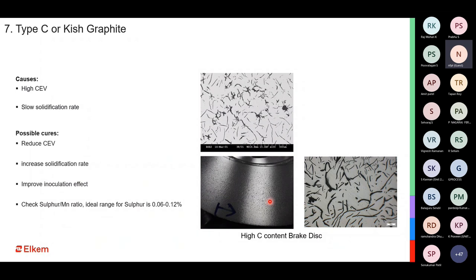When you machine a casting which has type C, you can see this type of pit marks, which are basically graphite getting pulled out because of their concentration in a few locations. How do you resolve it? Of course, you have to choose the carbon equivalent judiciously as per the section thickness. You have to try and increase the rate of solidification by using chills or something, so that you do not give the carbon sufficient time to agglomerate at one position. You have to improve the inoculation so that you create more nucleating sites for graphite growth, thereby distributing the graphite in several locations.